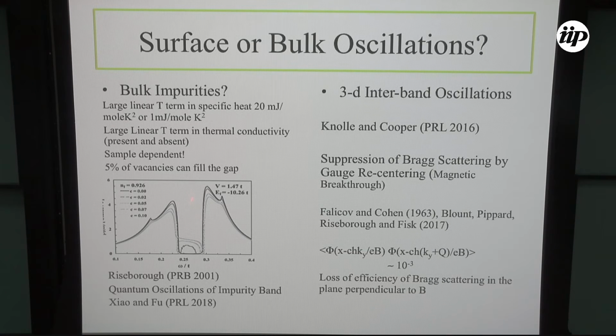This is because the gap is so narrow, and you have to use a sort of T-matrix approach, that for every impurity, every vacancy you have, it's a missing f state, and what you find is a bound state formed on all the nearest neighboring sites. And so it's a really large thing. So you can think about it percolating much more rapidly than a single impurity. So, okay, enough of that. So that's some things that may be going on with bulk impurities.